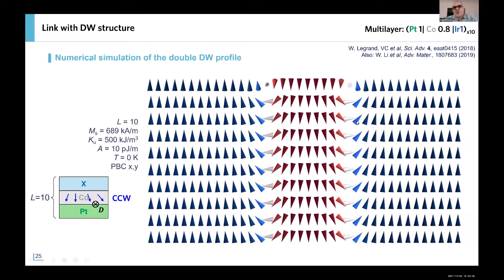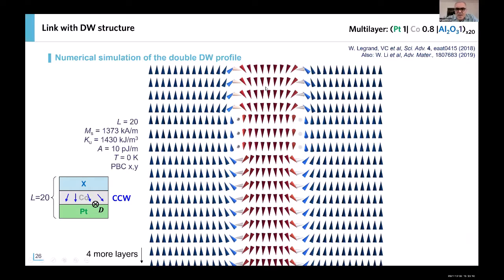But then, when you increase the number of repetitions, you have an increase of the role of the dipolar interaction, the dipolar field between layers, and this dipolar field has an opposite action compared to the field associated to DMI from the upper layers. And it means we start to twist the magnetization inside the skyrmion wall or the domain wall in the top layers. And this effect becomes even stronger with 20 repetitions, where you see that the effective chirality in the top layers is in fact driven by the dipolar fields, and at the bottom they are driven by the combination of dipolar field and DMI.